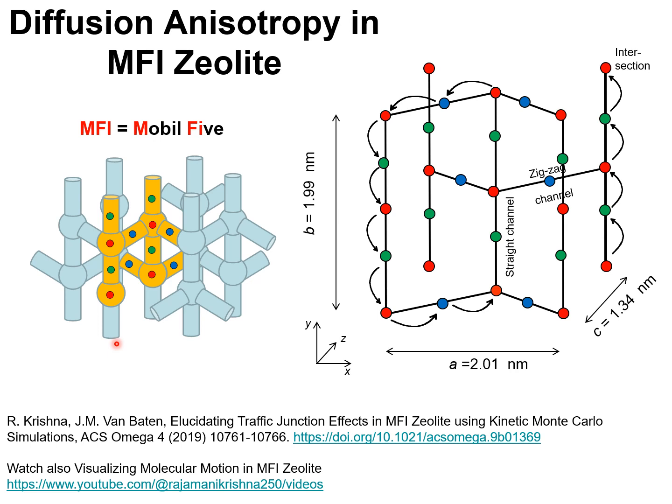intersecting channels: straight channels in the y direction, and zigzag channels. The channel dimensions are approximately 5.5 angstrom. The molecules can hop from one adsorption site to another along the straight channels, or hop along the zigzag channels.